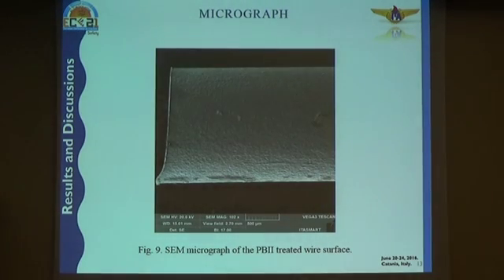This is a micrograph of our treated wire. There's a certain roughness in the surface. That's because we etched the wire before the treatment, because there was an intention of improving the cell adhesion in the surface of the wire for application. So we made this roughness, but I will show you that it's not so good an idea to make it.